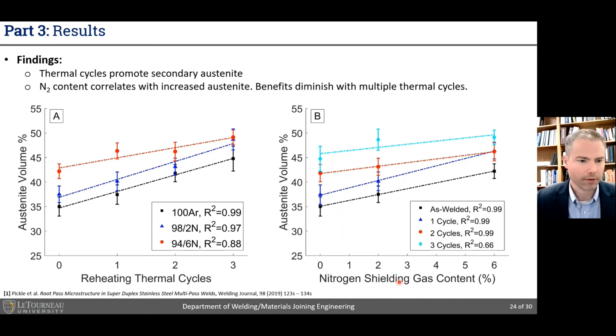So, plotting the results. In figure A here, we plot the austenite volume fraction for the 3 different levels of shielding gases as we increase the number of reheating thermal cycles. And significantly, from a practical standpoint, we see that by the time that we get to the third reheating cycle, there is effectively negligible difference between the 98/2 and the 94/6 shielding gas, which is consistent with industry recommendations to use the 98/2 shielding gas. There is an increase in austenite, it appears, relative to the 100% argon. And in this plot, figure B, we just plot this as a function of the nitrogen shielding gas content, which yields effectively the same conclusions.